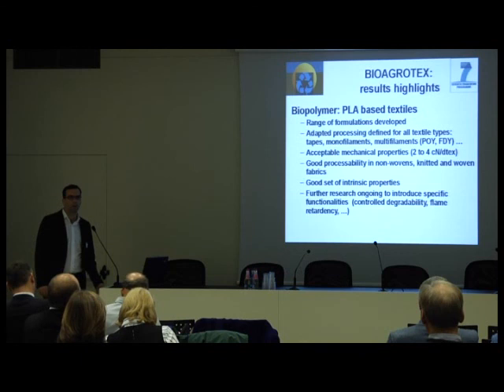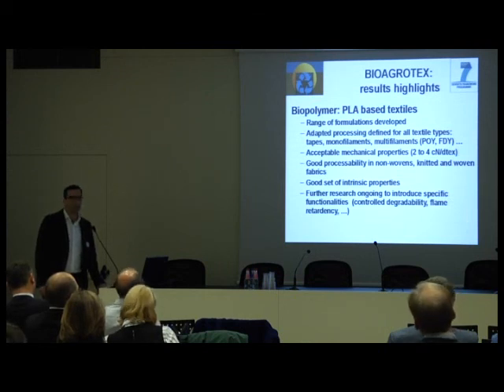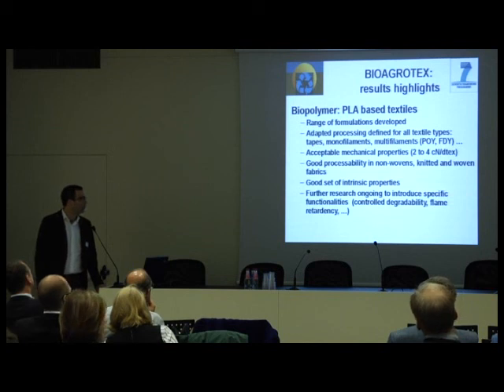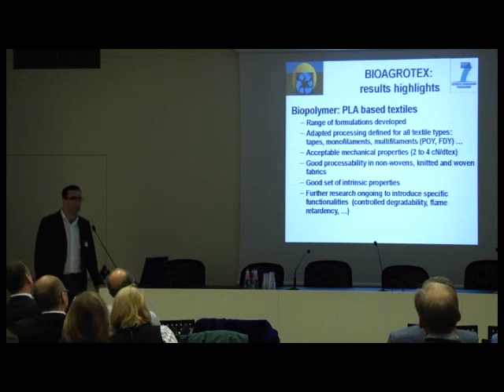On the side of PLA, however, we had quite good results with monofilaments, multifilaments, tapes with mechanical properties between 20 and 40 centinewton per tex. Good processability in non-woven materials, woven fabrics, knitted fabrics. So in this field we had some promising results, and we are also further elaborating to incorporate added functionalities such as controlled degradability, flame retardancy, etc.